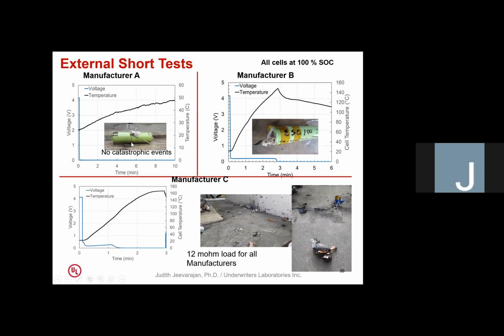Of course, manufacturer A has a PTC in it, so we didn't see any catastrophic failures. The PTC gets activated, and we didn't see any high temperatures at all for the 3 hours. I'm showing only a little bit of the test here, but we held the short circuit for 3 hours.